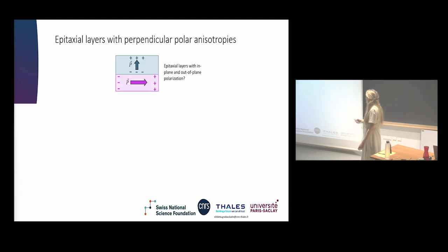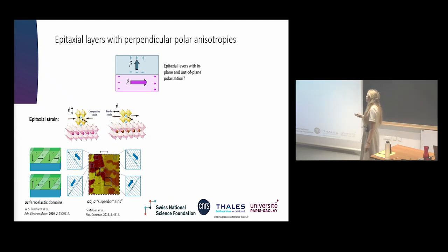The idea is to grow something that's mostly in-plane polarized, and on top of that grow this out-of-plane polarized film, in hopes that there will be no critical layer or so-called dead layer. The way you can achieve in-plane polarization, because in fact most of the typical ferroelectrics like BTO, PTO, PZT are all out-of-plane polarized when grown epitaxially, and it's quite rare to come across something that has purely in-plane polarization. To achieve that, one can look into epitaxial strain. Of course we can strain the unit cell in the plane, but typically one ends up with some a/c domains, so still some coexistence. One has some A superdomains with different polarization directions, so it can be messy.